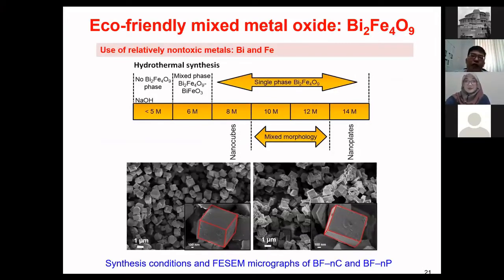So that means copper-based catalysts may not be so relevant if you want to scale it up. So the next thing we will look at is bismuth ferrite. I consider this bismuth ferrite as one of the best catalysts for this application. And bismuth and iron are relatively non-toxic compared to copper and cobalt. So this bismuth and iron, we combine it to make a material, and we control the morphology.